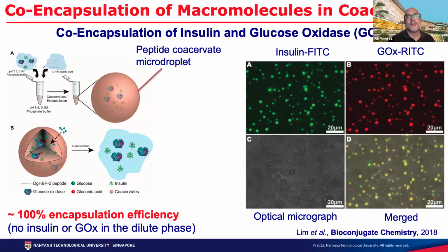But when we were working on this, we found something very interesting. My student was doing some cell culture, and he found those droplets inside the cell, which is very intriguing because if anyone works on drug delivery here, usually the consensus is that you have to have vectors that are below 200 nanometers to deliver inside cells. But those droplets are 1 to 2 micron. So it's very strange. So they stay inside the cell, but they wouldn't disassemble.